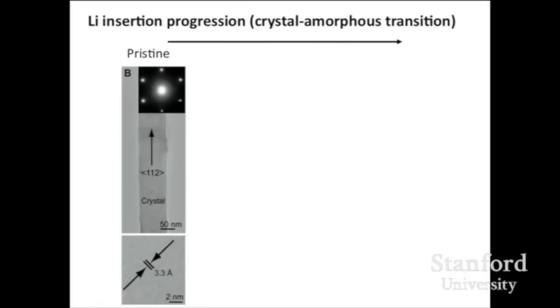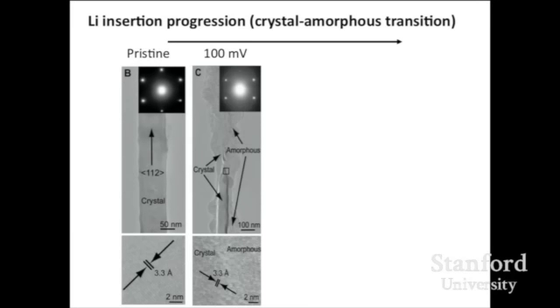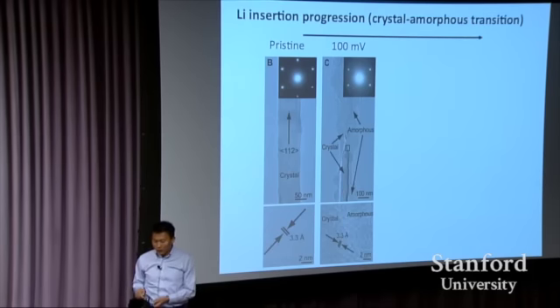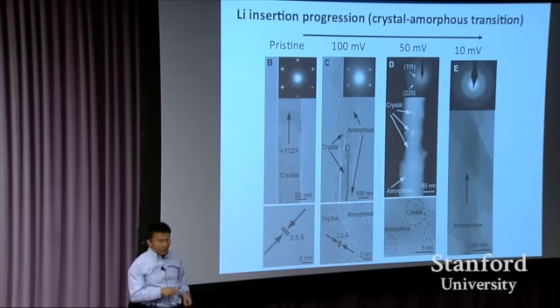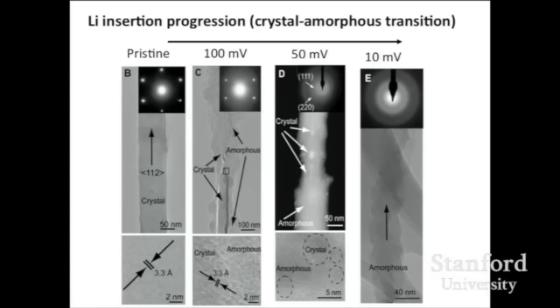And then we started to find out this change is really dramatic. This is a single crystal silicon nanowire to start with. You put lithium in, you see this become amorphous. This remains partially crystalline. Eventually, the whole thing becomes amorphous. This big volume expansion is happening. What this really confirmed is that crystalline silicon becomes amorphous. Lithium comes in, breaks all the silicon-silicon bonding, and reforms lithium-silicon bonding. At room temperature, silicon and lithium's mobility is limited. Silicon and silicon cannot reform and come back to the crystalline phase, so they stay as an amorphous phase.